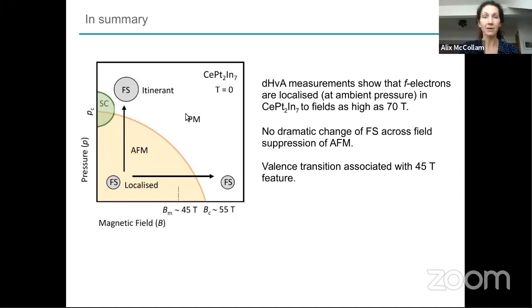There isn't actually any evidence of a crossover here, only that it must be there, because we know at low field at least, in this region, that there's an itinerant Fermi surface, or this has been reported. And in this direction, we see that it's still a localized Fermi surface, so it's small here and large here. So there must be a crossover, but we don't have evidence of it. This is, in a way, the dream experiment, to go to 50 Tesla and go up in pressure.